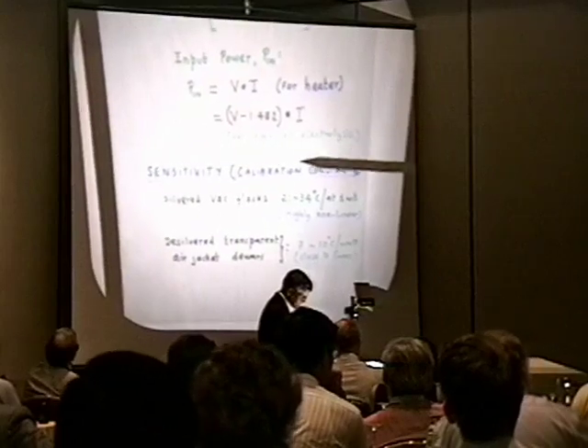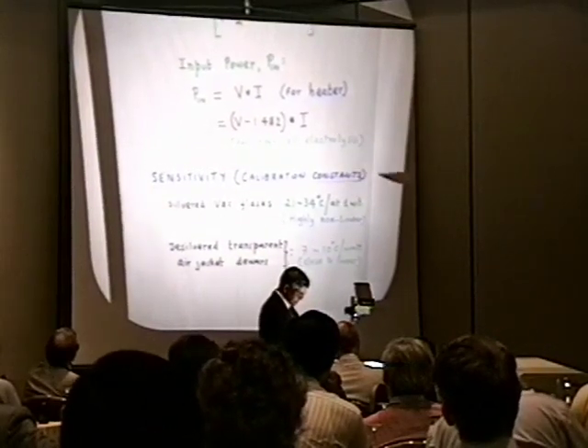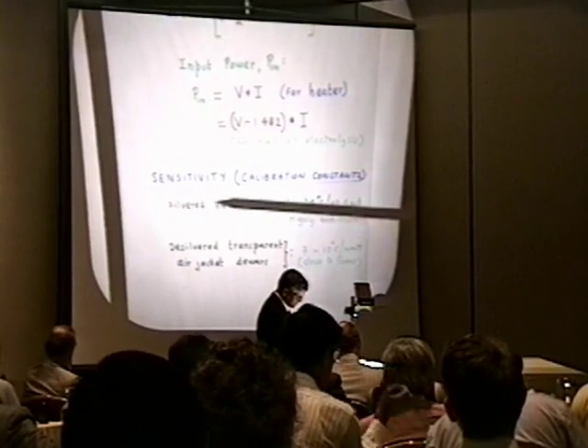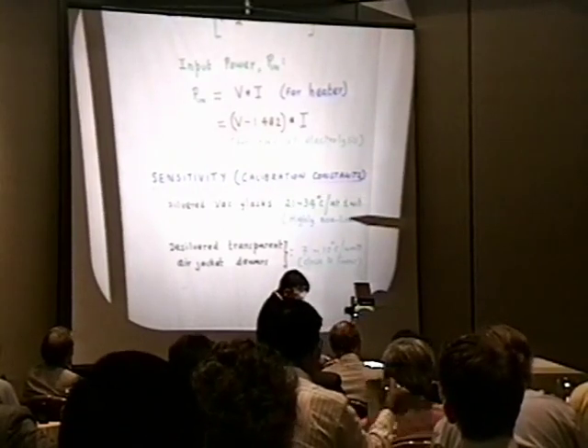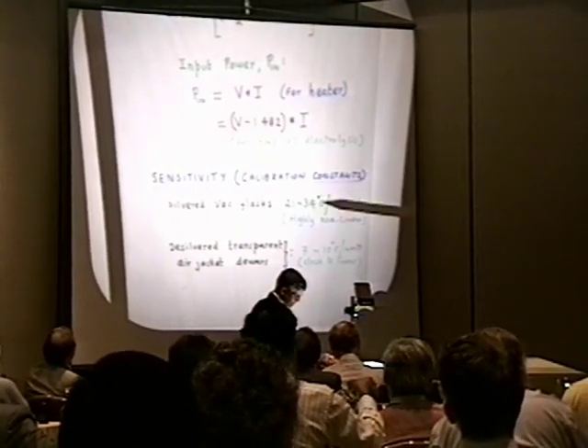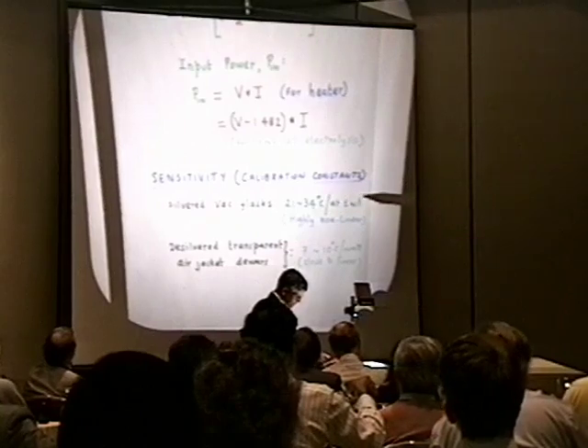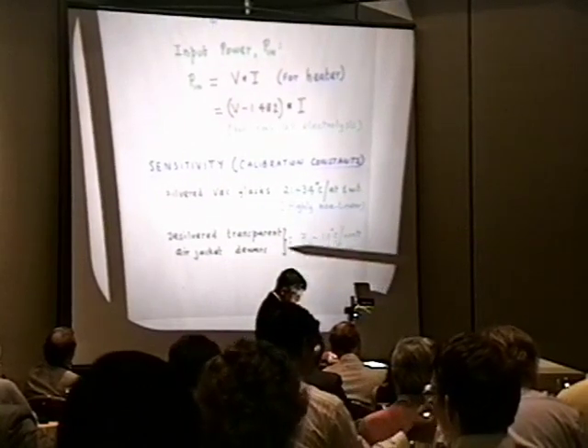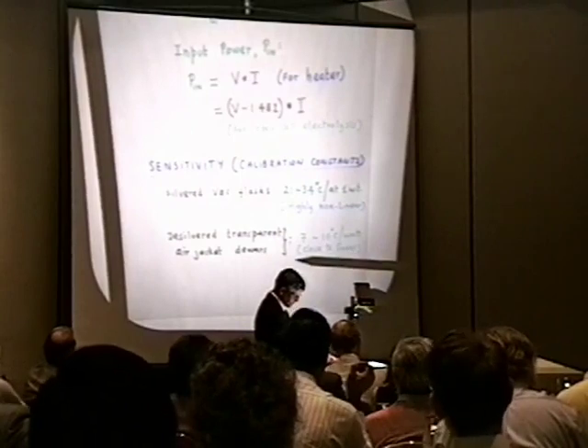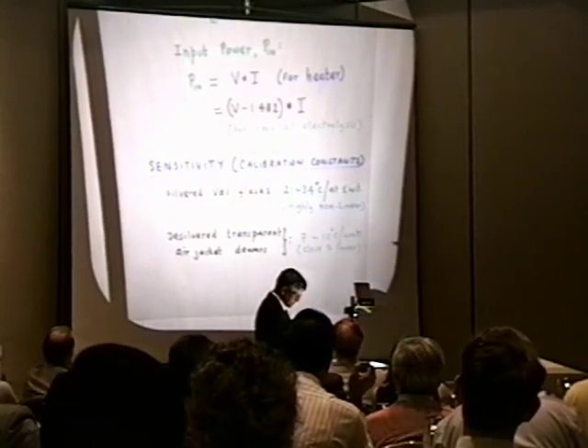All quite standard. The sensitivity or the calibration constant in the case of the silvered vacuum flask, the calibration curve was highly nonlinear, varying somewhere between 21 to 34 degrees C per watt, whereas the desilvered flask which we used subsequently, we used to get almost linear curves in the region of 7 to 10 degrees C per watt. At this point, I would like to quickly go through the slides, just to give you an impression.